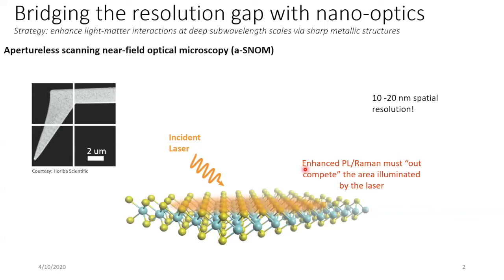The general problem is if you're doing confocal microscopy, you have a focused laser spot and a TMD with a pretty broad area that's going to be illuminated. The strategy is to couple your incoming photons to some sort of light-matter interaction. The light-matter interaction here is provided by the plasmon at the surface of a metalized AFM tip. We're going to set a localized surface plasmon as an oscillation of the localized electrons in the metal that is the local source of optical field and will enhance the field right below the tip.